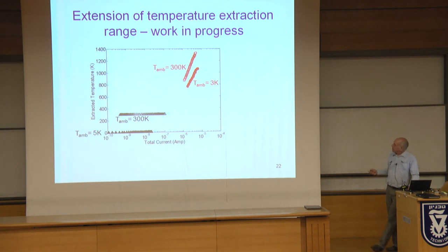So here are the temperatures we have extracted as a function of the total current. We repeated the measurement also at low temperature just to make sure that we are really measuring temperature and not something else. We are expecting the temperature to be lower, and this is actually the case. Extracted temperatures are about 300 degrees lower at 3K than at 300K. So this made us believe that our results are correct and we are extracting the right temperature. We can extract high temperatures, we can extract low temperatures, actually showing that we are doing our job correctly.